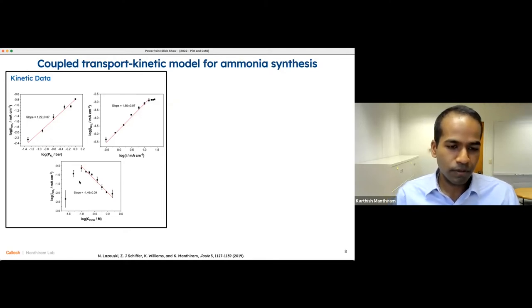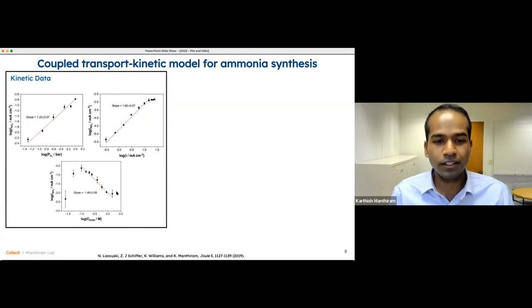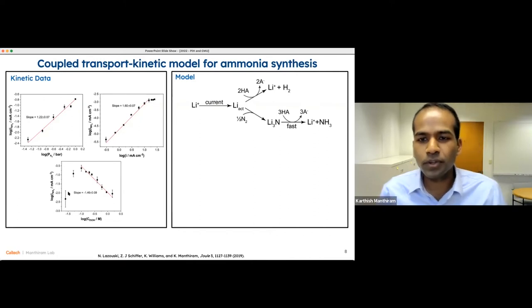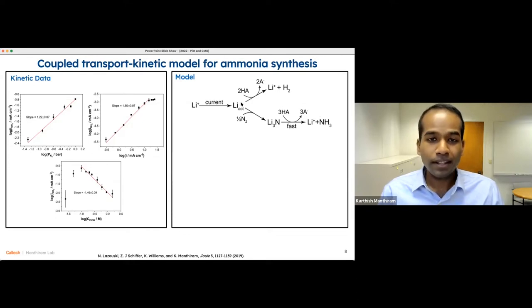This makes sense just from the perspective that if there's too much ethanol, we would have uncontrolled hydrogen evolution. And if there's too little ethanol, then we don't have the proton donor that we ultimately need to protonate the lithium nitride to make ammonia. So we can develop a really simple model that helps to account for many of these different features. First, this plating of lithium ions to make lithium metal, that lithium metal then going down one of two branches. The productive branch is reaction with nitrogen to generate lithium nitride, and that lithium nitride could then react with proton donor to make ammonia.